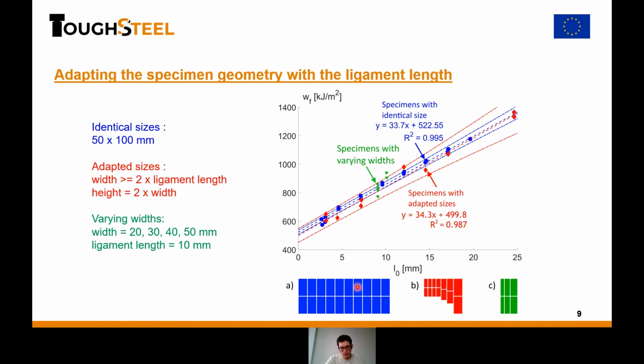This comes from two contributions. The first one is simply statistics, because for the blue set of experiments we used 20 samples, and for the red one there are only 14 samples. But also, something I will show later, it's a bit hard to handle smaller samples, so we had a bit of difficulty performing the mechanical test. And the last thing I wanted to show in this slide is what you see at the bottom of the graph, which is a representation of the total amount of material needed for each of these points. Just at a glance, you can see that the red one uses a lot less material than the blue series.